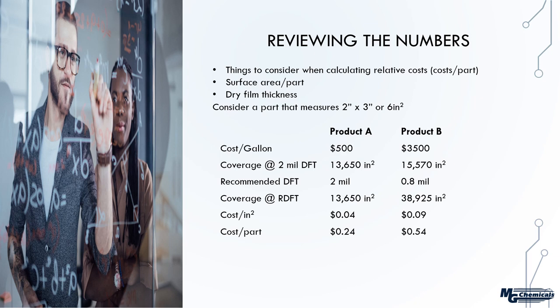But now let's take into account the recommended dry film thicknesses, and maybe this particular product you can apply at a much lower thickness. So in this example, instead of 2 mils, you have 0.8. So again, it's a fraction of product A, and that's going to narrow that gap as well. So when we look at the coverage in terms of what's recommended, now we're almost at 39,000 square inches compared to 13,650 in the first example.